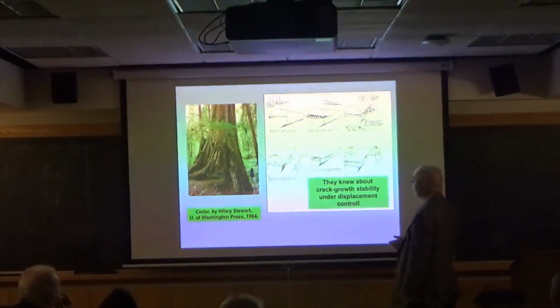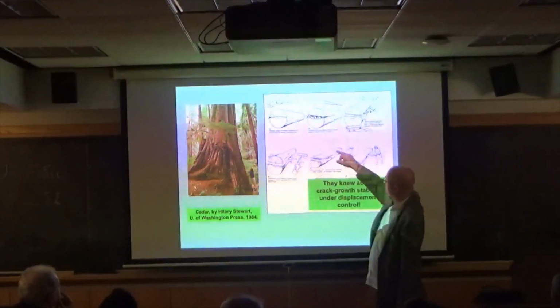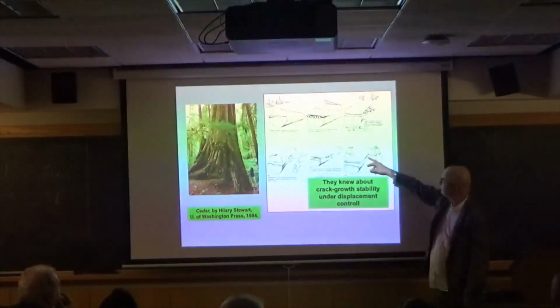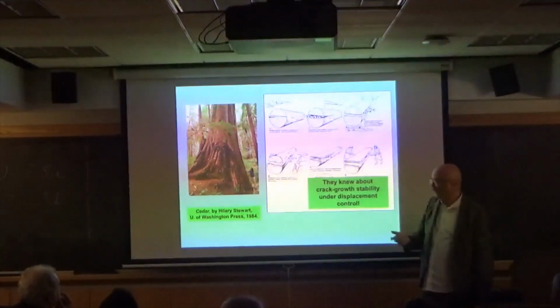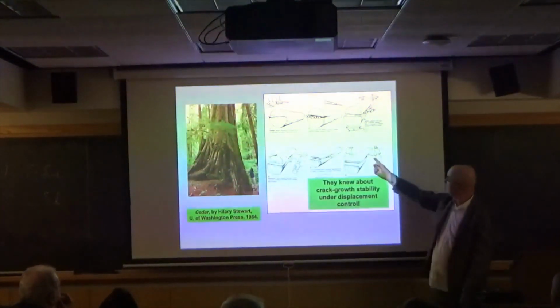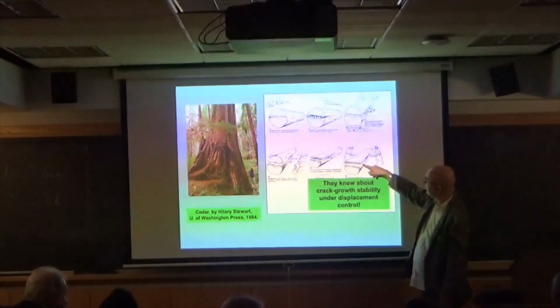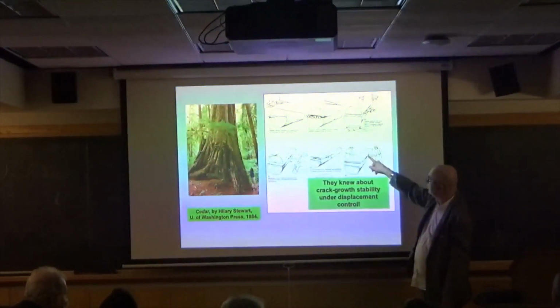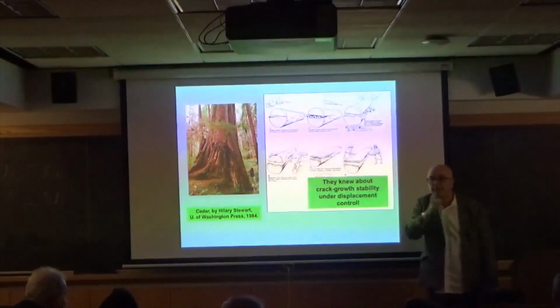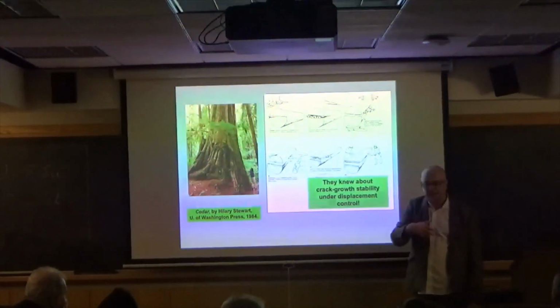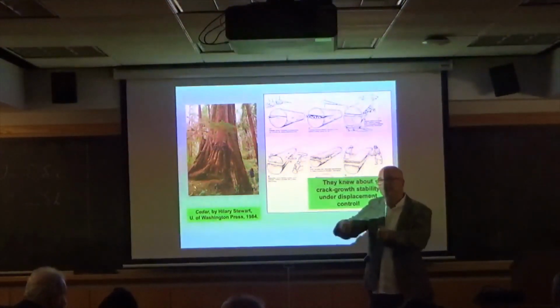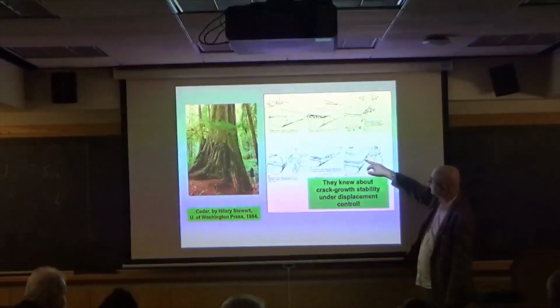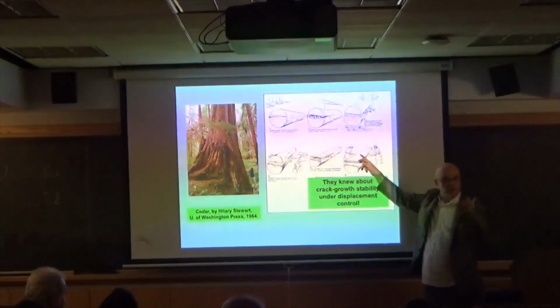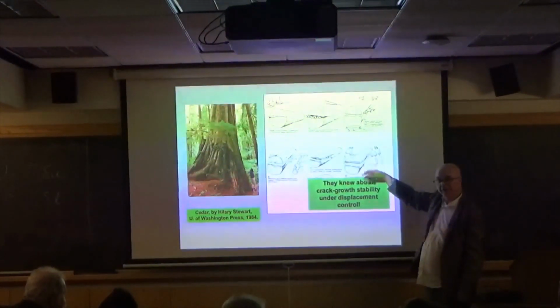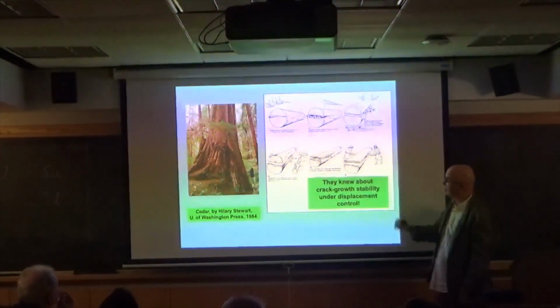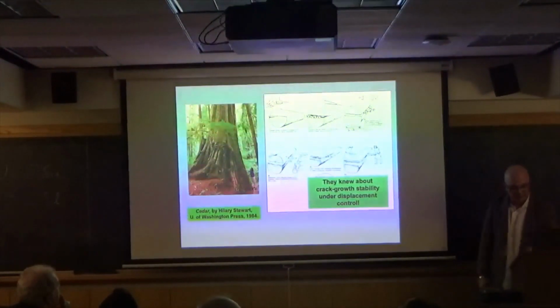So for example, if they wanted to fracture a plank so they could use it to build perhaps a house, they would put perhaps a rod here, but they knew about what's called crack growth stability. It turns out in this configuration, if you start fracturing here, and the crack starts extending, the crack stops because this is what's called a stable configuration. The energy release rate is a negative function, so you need to keep on driving it to make the crack propagate. So what they're doing is they're moving along here, which is intuitive, to keep the crack from growing. And again, you can explain this mathematically now through energy arguments and stability arguments.